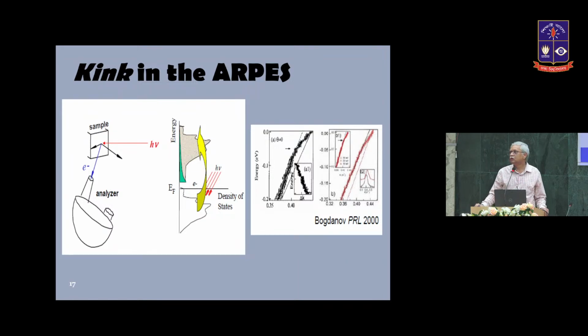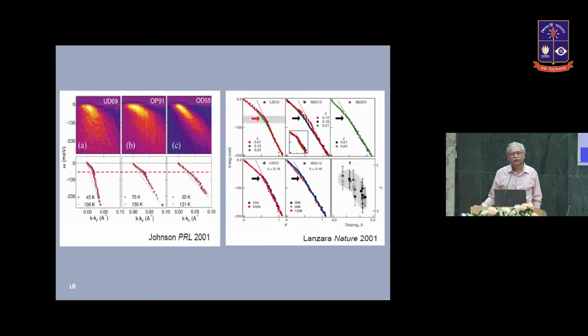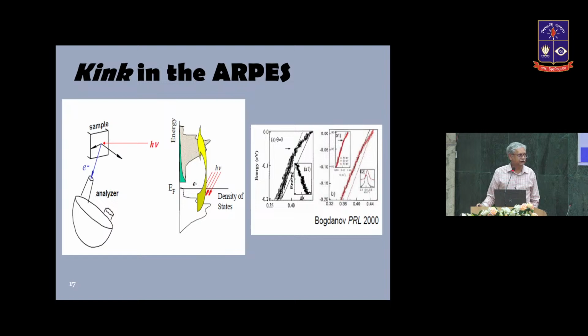So in the morning session, Professor Zahid Hasan talked about ARPES. The technique has advanced so much. If you look at the electrons which are photo-ejected, you can actually find out from which orbital, with which k value, and from which part of the Brillouin zone it is coming out. And if you map that result, you can see in copper oxide superconductors there is actually a kink. So something is coupling with a bosonic mode, and that is quite conventional. But identifying this particular bosonic mode is a challenge. These are all those ARPES results, and in all those figures, you can see the kink in the electronic dispersion.